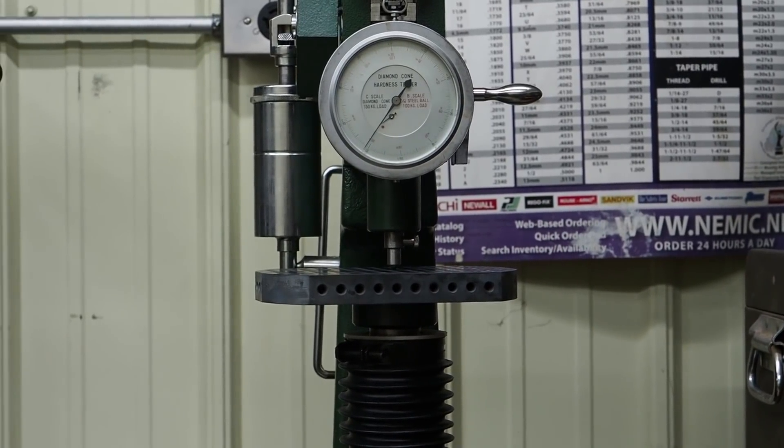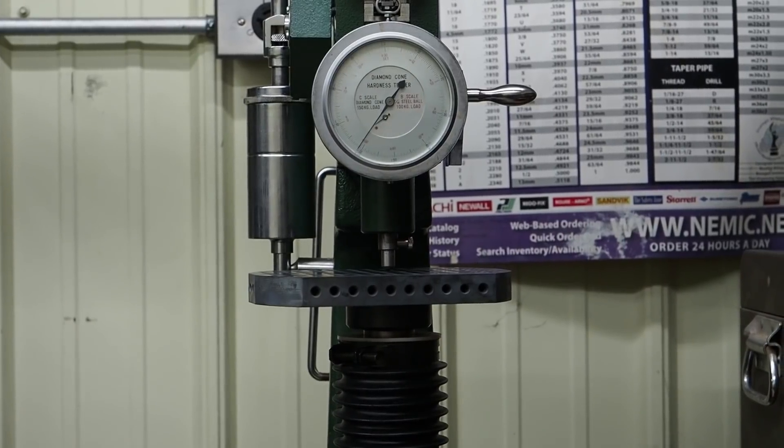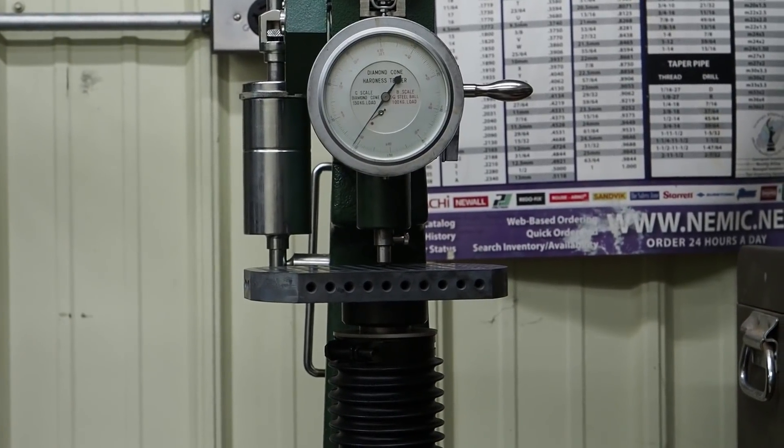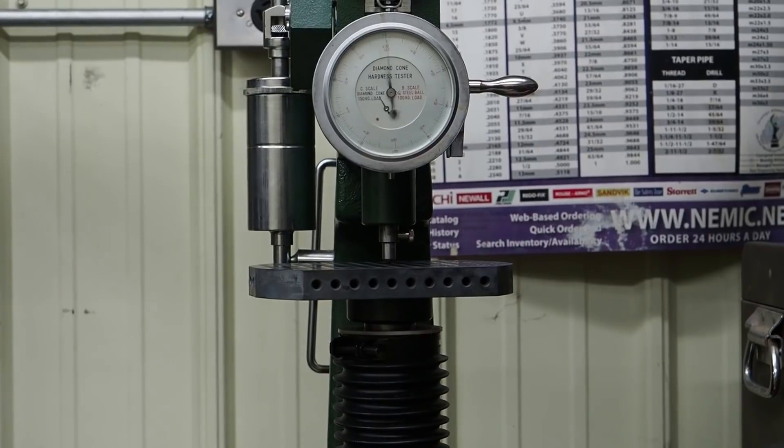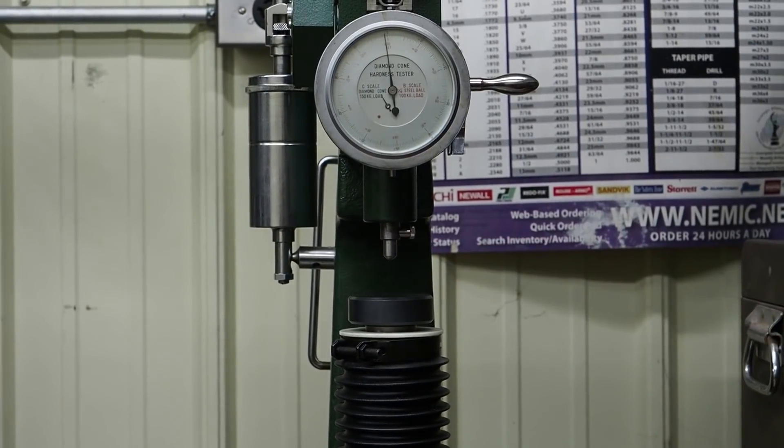It's over 60 — we're going to draw back. We'll shoot probably for 58 to 59. We'll go over to the computer now and show you where we do the settings on that.